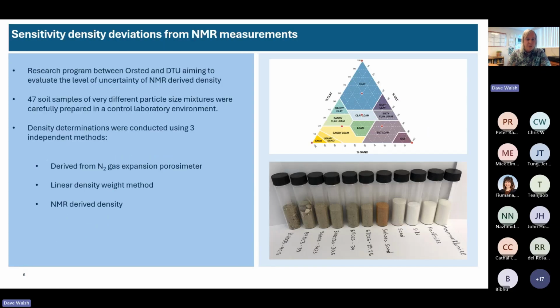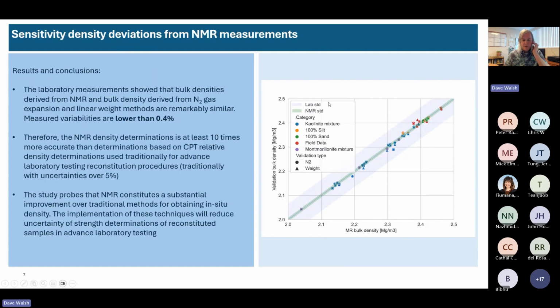So as part of their internal research, Ørsted and another institution also performed some laboratory work to establish the relationship and the suitability of using in situ magnetic resonance measurements to estimate, in particular, density. And they found through these measurements that in situ NMR measurements of porosity combined with the a priori assumption of dry density is a very accurate and very precise way of estimating the bulk density in situ.